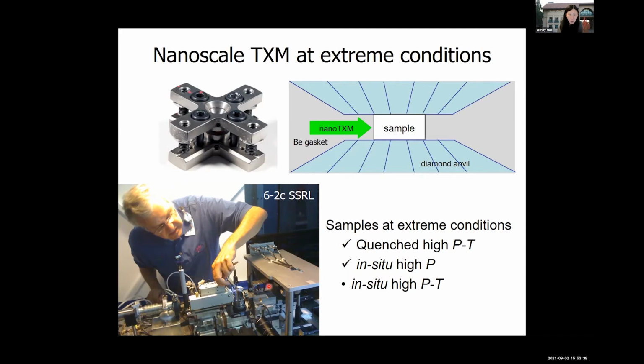So, where are we now? We can look at quench samples really well. These are samples that are synthesized at high pressures and temperatures, and then recovered back to ambient conditions. We cut out a small portion of our diamond cell sample and image that. We also can couple a diamond anvil cell for in situ high pressure imaging at room temperature.